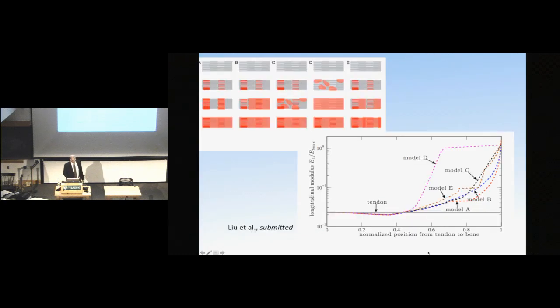And so here's the final outcome. The final outcome is that this is a stiffness, or modulus, in the axial direction of the combined tissue going from tendon to bone, combining all these data for the 5 different models of mineralization that we considered. And the key is that all of them predict an initial drop in the stiffness of tendons. So despite the linear increase in mineral, the orientation distribution, shifting from collagen being organized in tendon to disorganized in between, causes a drop in the stiffness. And then at the percolation threshold, there's a rapid rise.